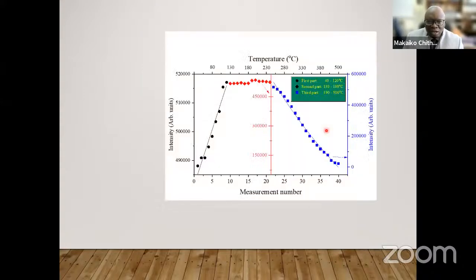Again, if you compare the model with experimental data, you can see that the prediction of the competition effect is quite good, and also the decrease that occurs afterwards due to preheating is well predicted.